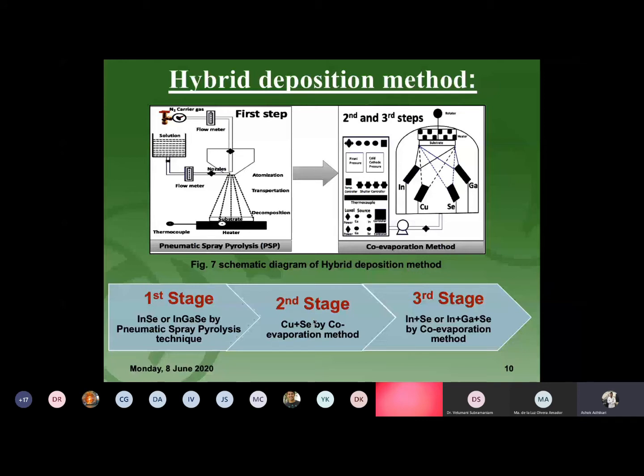The first stage of the hybrid deposition method involves the deposition of indium selenide or indium gallium selenide by pneumatic spray pyrolysis. In pneumatic spray pyrolysis, a growth solution process, small droplets of the precursor solution are spread on the heated substrate.